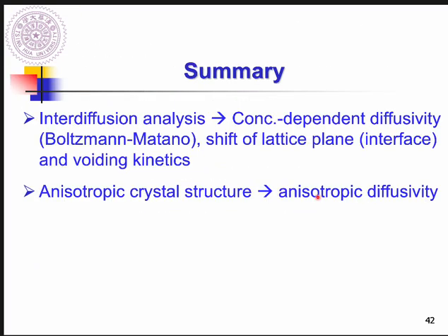Sorry, so I'm going to give you a quick summary here. For interdiffusion analysis, in order to know whether you need to perform the Boltzmann-Matano analysis, you need to perform your experiments to get the concentration profile, to help you recognize whether the diffusivity changes with concentration or not. Then you can make a decision whether you need to use Boltzmann-Matano analysis to help you get D at a specific concentration of interest.